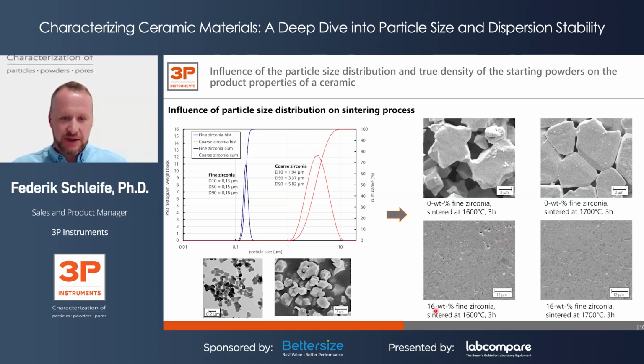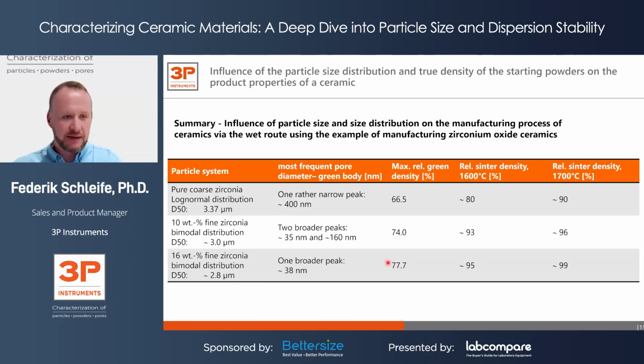But when we take the 16 weight percentage fine zirconia and 84 weight percentage of coarse zirconia, and we perform the sintering process at 1600 degrees Celsius for 3 hours, we can achieve an almost really dense structure with only a few pores left, as you can see here on this image. But then increasing the temperature to 1700 degrees Celsius for 3 hours, you could see that you can really achieve a closed structure, and you can expect a good performance of the final ceramic workpiece here. So therefore, I could show you that adjusting the particle size distribution of the raw material you will use for the process has dramatic influence either on the green body properties, and furthermore also, of course, during the sintering process on the final ceramic piece.